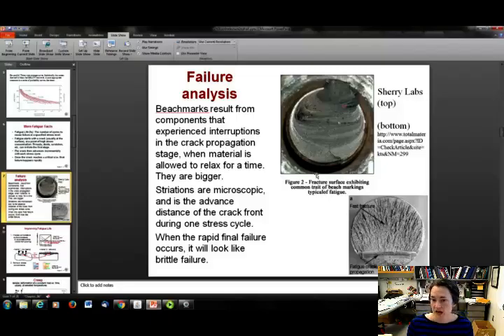All right. Now, down here in the lower right-hand corner is a part from a totally different website that I've cited here. And what that looks like, it'll show you the crack formed, it initiated down here at the bottom, and then you have your kind of beach mark looking pattern down here until the crack advanced far enough, the flaw advanced far enough that boom, you've got your brittle fracture failure, and this is what that surface looks like. Okay? So you can figure out a lot from that fractography.